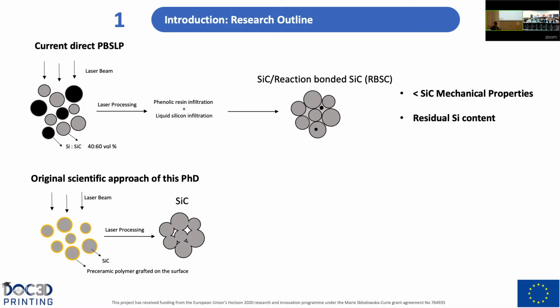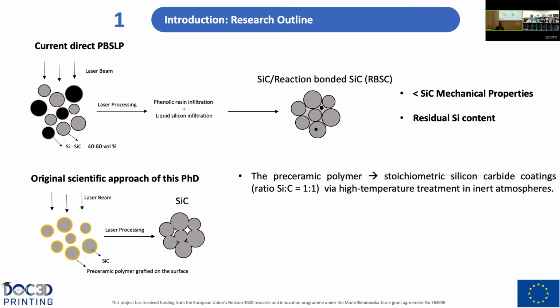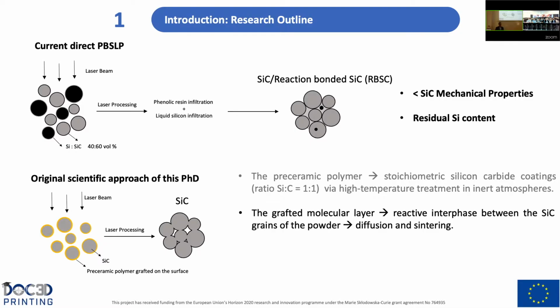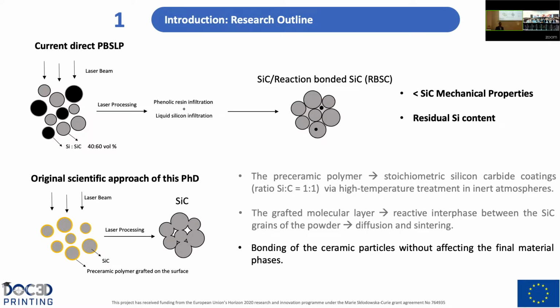But what's the original scientific approach of this PhD? Here, what we want to do, instead of using this silicon powder, is to graft a preceramic polymer on the surface of the silicon carbide. So what are the features or characteristics that we need in this preceramic polymer? This preceramic polymer will create a stoichiometric silicon carbide coating via high temperature treatment in inert atmospheres. Then this grafted molecular layer will create a reactive interface between the silicon carbide grains of the powder, facilitating diffusion and sintering. Next, this will produce the bonding of the ceramic particles without affecting the material phases of our parts.